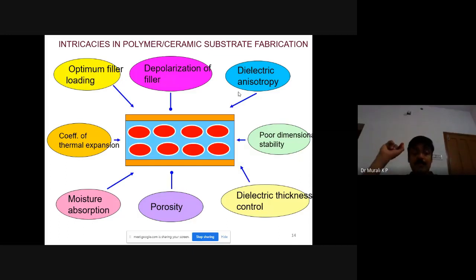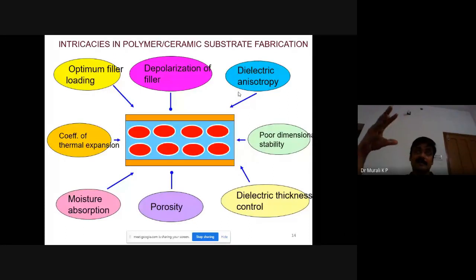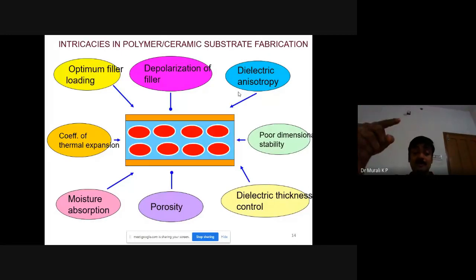Next one is moisture absorption. Moisture absorption is related with the porosity. So if you want a very high dielectric constant substrate, you just can't fill a very high volume fraction, because once you cross a particular threshold level, it will create a lot of porosity in the composite, which will lead to moisture absorption and weaker mechanical properties. Its strength will come down. So that is another point to be taken care of. And then dielectric thickness control, you have to take care. That I was telling about, the restriction or tolerance in the thickness level. And poor dimensional stability. Yeah, because dimensional stability means with respect to temperature cycle, this dimension should not get changed. So that you have to take care of.